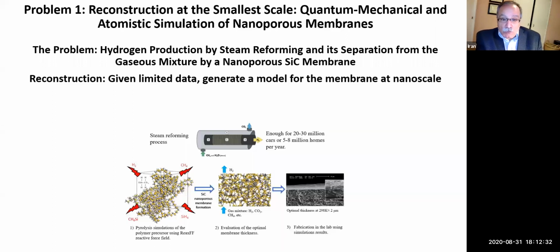A good membrane should have high flux and also high separation factors. In other words, it should be able to purify, for example, hydrogen and separate from the rest. But high flux means very thin membrane, because as the thickness increases, the probability of having defects in the structure increases, and therefore you lose separation. On the other hand, if it is too thin, then it cannot withstand the high pressure that you apply during the operation. Therefore, there's an optimal thickness that you have to identify, and this is something that we wanted to do.